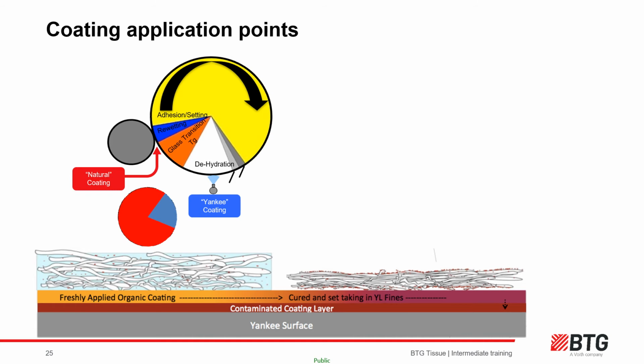The contaminants will migrate to the hottest part of the sheet as shown. Some of the contaminants may be chemically fixed or retained to the individual fibres to stay within the sheet. This is where the drying bias we have discussed earlier is important, as more contaminants will tend to migrate to the hotter side of the sheet. So, some will go to the hood side and some to the Yankee side.